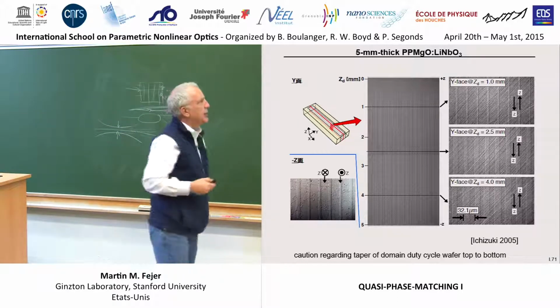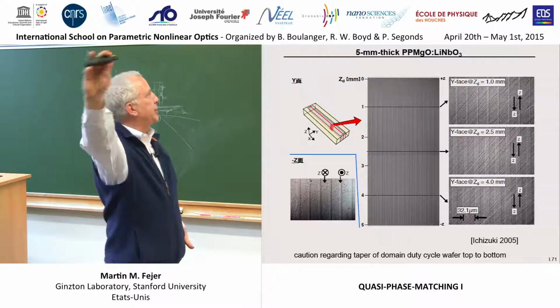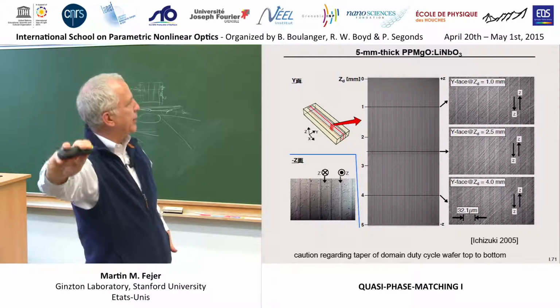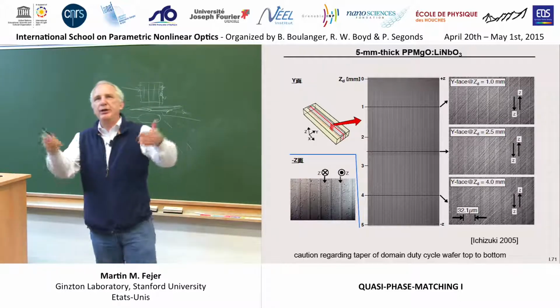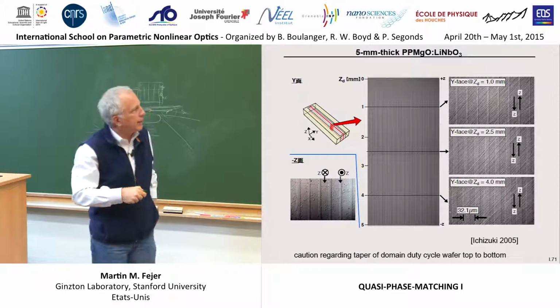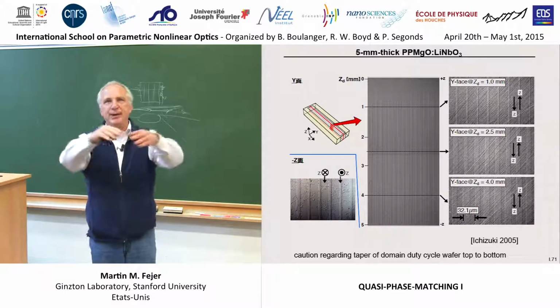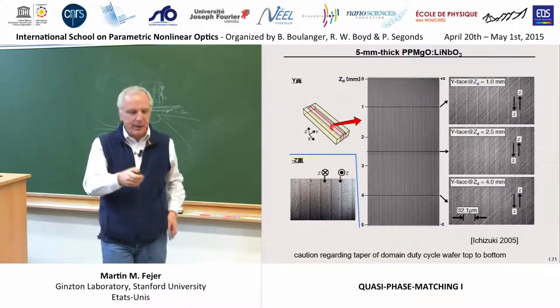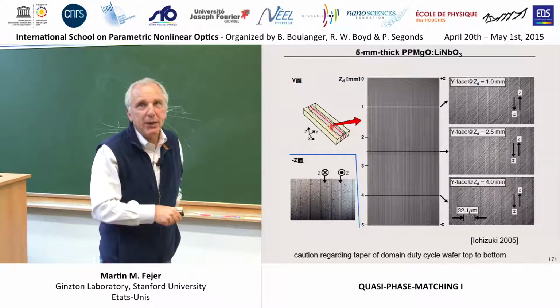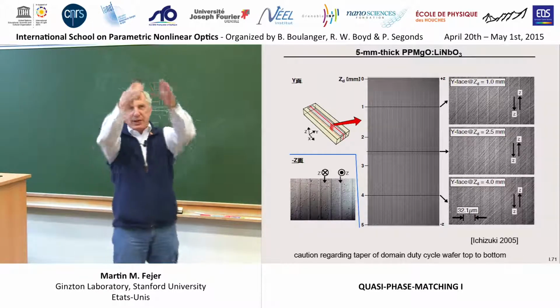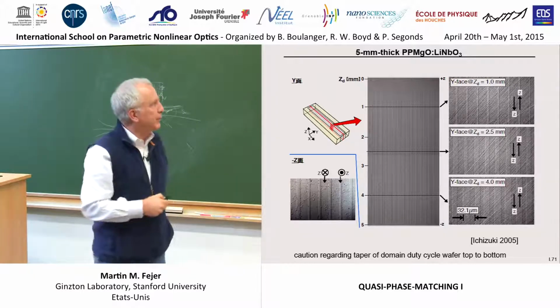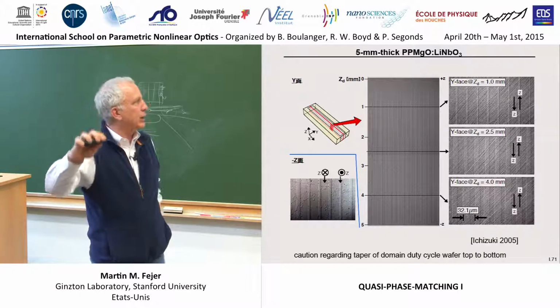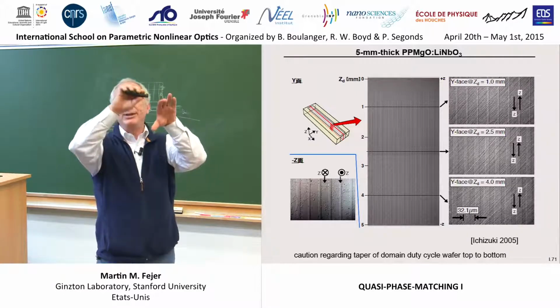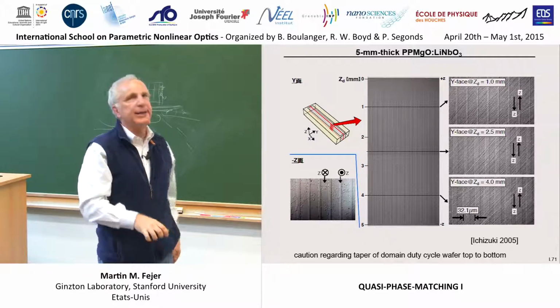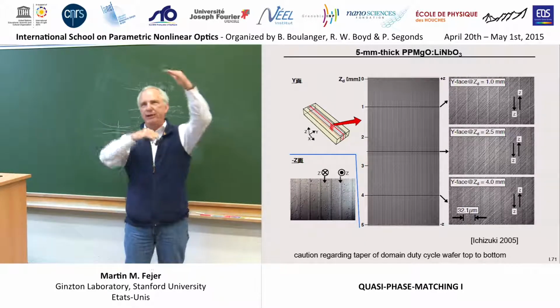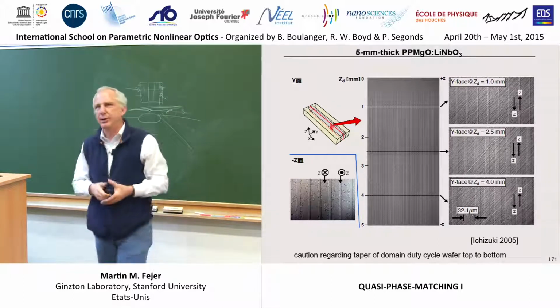So if you had such a sample, the empirical observation would be if you sent your laser beam through the top of the crystal and the middle of the crystal and the bottom of the crystal, you would see a different nonlinear behavior. Basically, if the middle is 50% duty cycle and gave you the largest nonlinear susceptibility, we said you wanted a 50% duty cycle, right? Then you'll do worse near the top and near the bottom because the duty cycle is different from 50% because of this taper of the width. So if you're playing around with unknown samples, it's not a bad idea to do a little bit of mapping and seeing where the performance is best, because these kinds of inhomogeneities still exist, especially as you're pushing the envelope, trying to get to very thick material or very short period gratings or things like that.